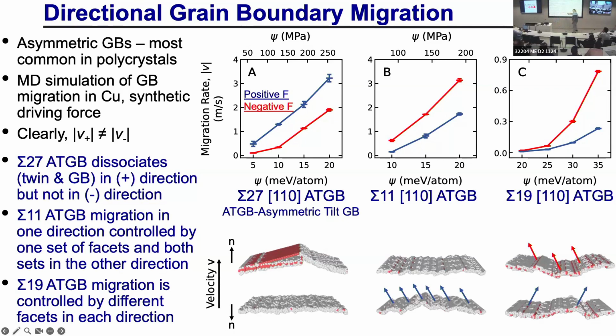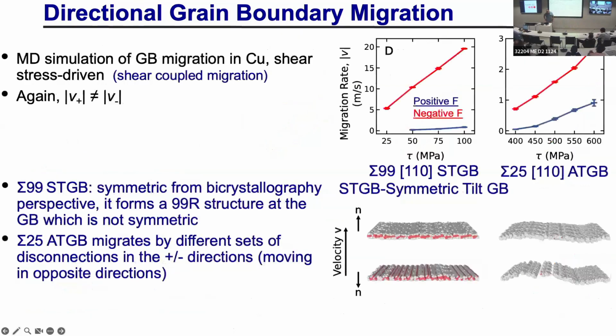So what this boundary does here is completely different than what this does. And every time I look at an asymmetric boundary, it seems to move asymmetrically in the different directions by completely different mechanisms. But it's not surprising that once the structure is different, the mobility is different. Okay? And it turns out that as long as the boundary is asymmetric, the boundary will always find a way to move with different structures in different directions. Okay, a couple more examples, and then we'll spend most of the time today on the analysis.